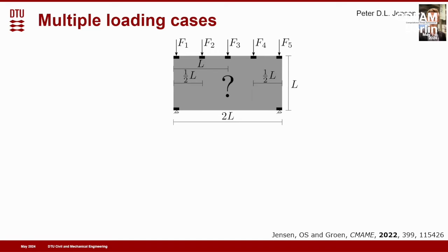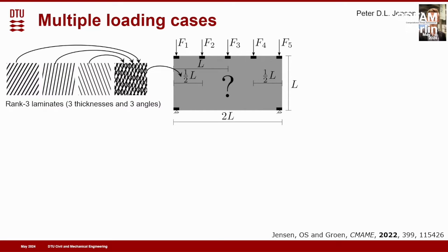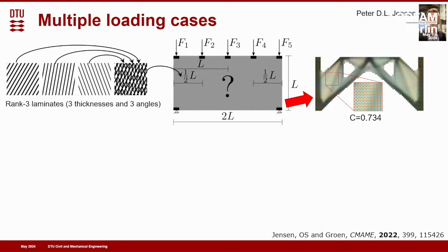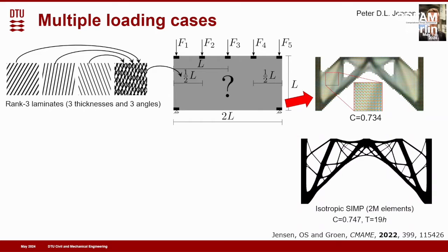And so this is a standard test case in the field here, 5 load cases. We need to distribute now 3 different lamination directions. There are formulas to do that. This is a homogenization-based solution, again with these mushy gray pictures. As a reference, we can do a topology optimization, just a crude Matlab implementation with a very fine resolution. We can get a compliance that is just a few percent, or 1%, I think, above this theoretically optimum structure here. But it costs almost a full day of CPU time on a laptop PC.